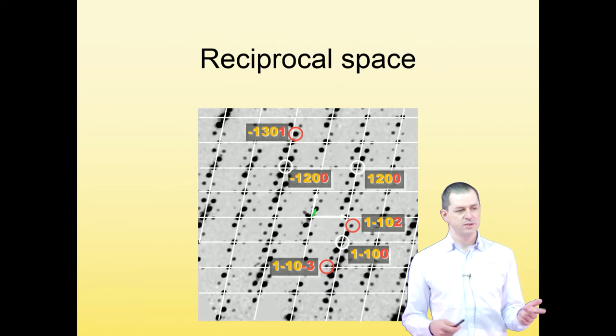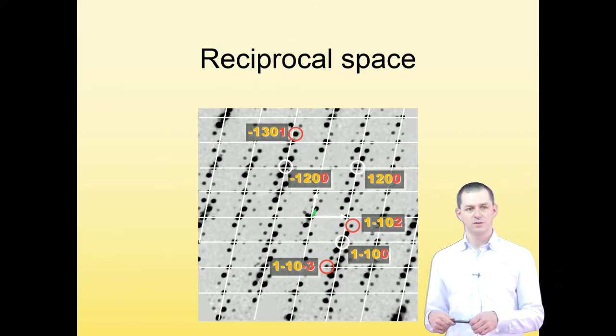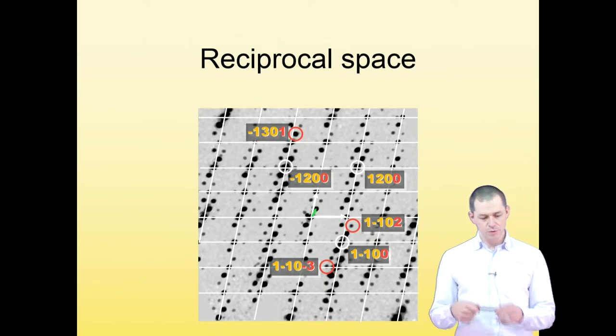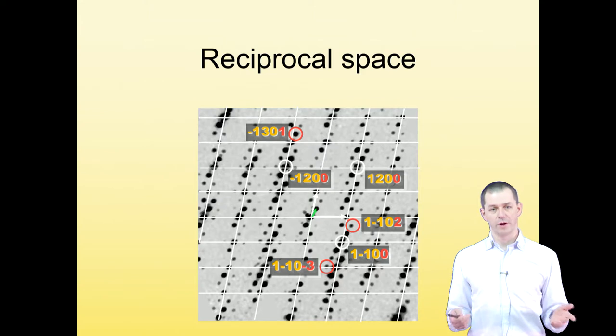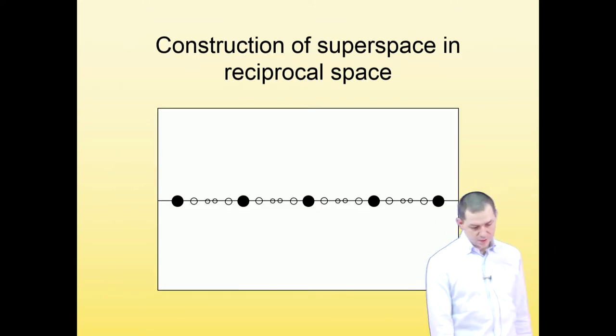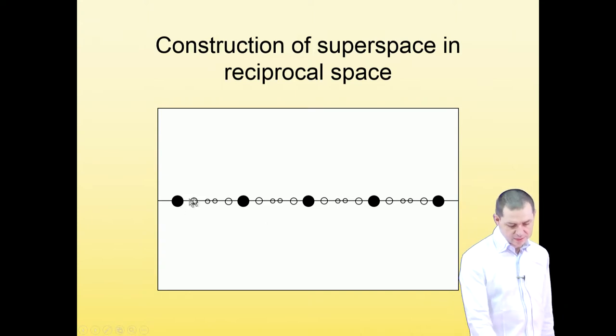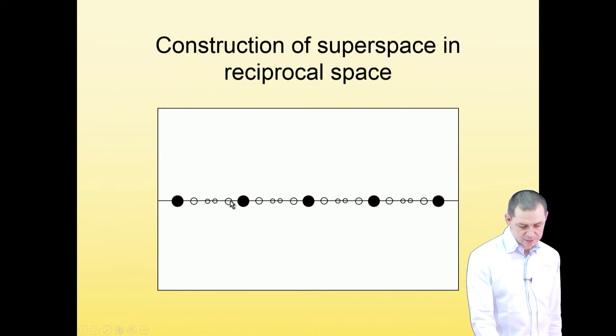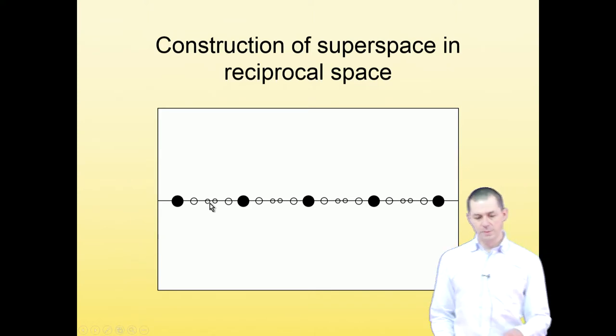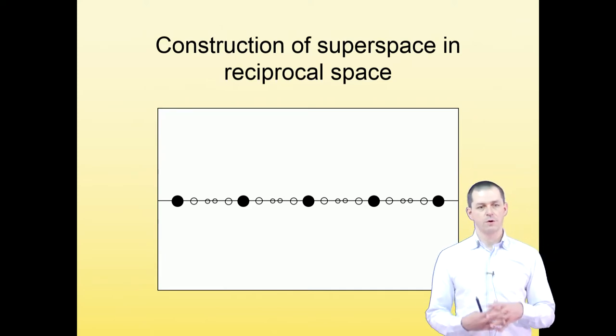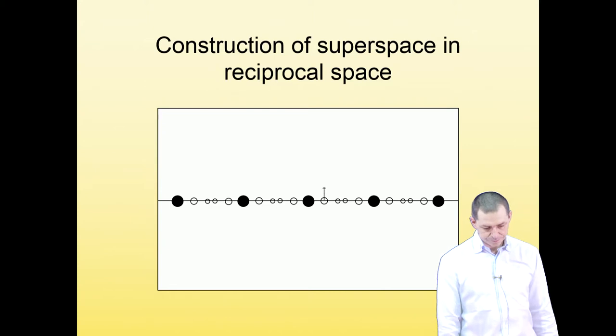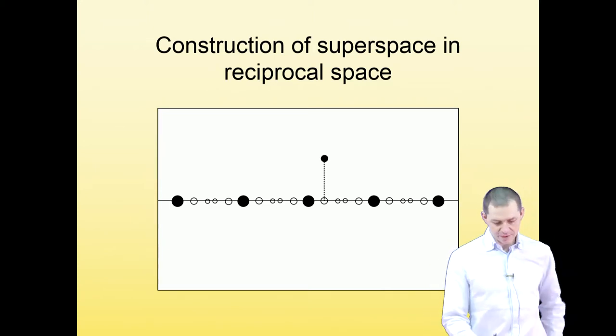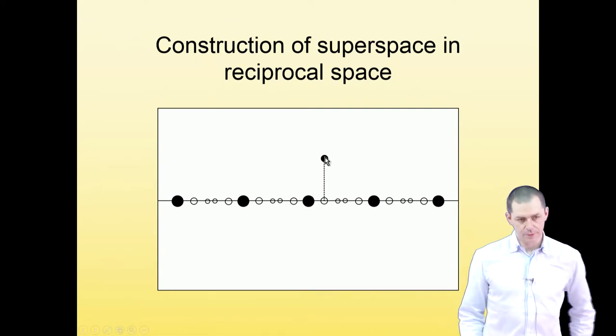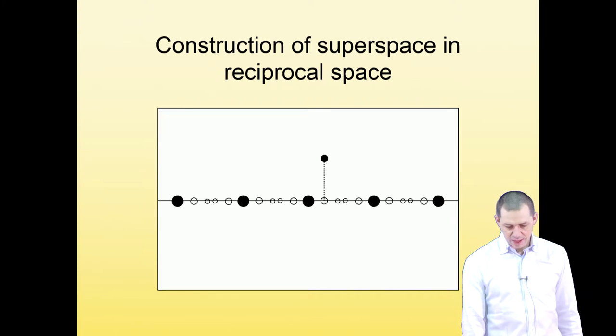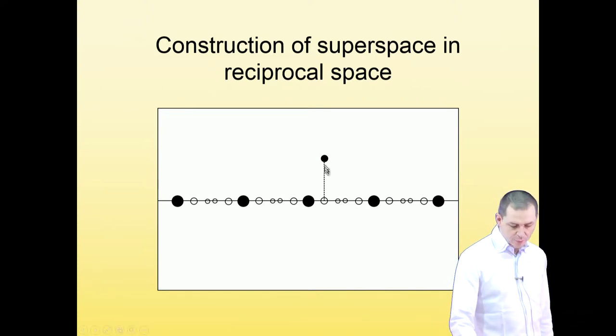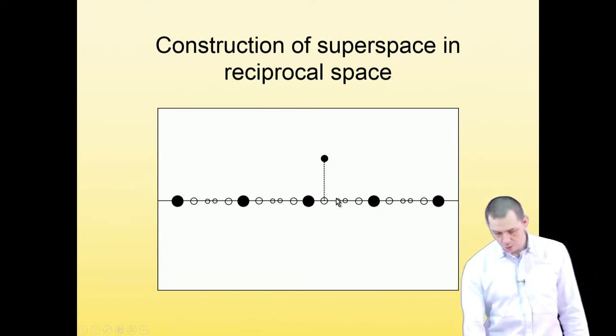And 3 indices are necessary to index reciprocal lattice in 3 dimensions. By analogy, 4 indices can be used to index reciprocal lattice in 4 dimensions. So we can actually imagine that the diffraction pattern, which here has these main reflections, and these are the first order satellites, and these are the second order satellites, is obtained as a projection from a higher dimensional reciprocal lattice. So we unproject, we lift the satellites up from the reciprocal physical space, and we lift them up with a multiple of certain length that corresponds to the order of the satellite.